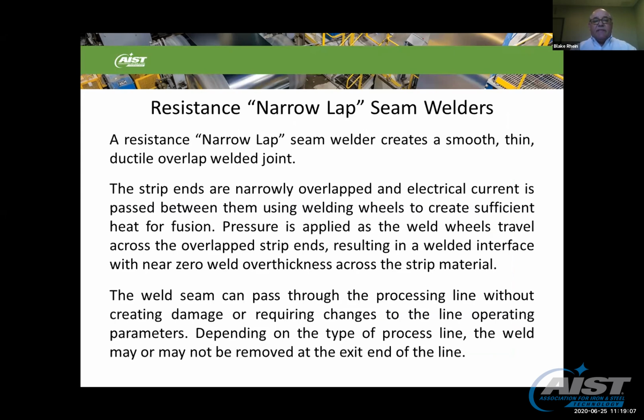In the case of resistance narrow lap seam welders, a resistance narrow lap seam welder creates a smooth, thin, and ductile overlap welded joint. The strip ends are narrowly overlapped and electrical current is passed between them using welding wheels to create sufficient heat for fusion. Pressure is applied as the weld wheels travel across the overlapped strip ends, resulting in a welded interface with near zero weld over thickness across the strip material.